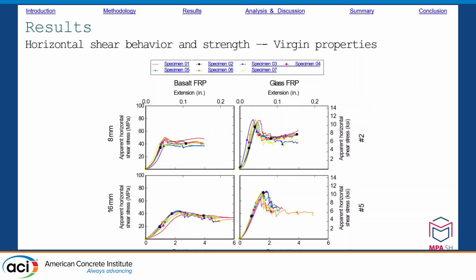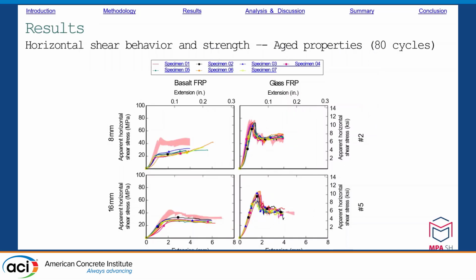The result graphs of the specimen tested for the apparent horizontal shear strength also show an increase until the maximum shear stress is reached. After that, the graph levels out and no further increase can be seen. The glass fiber rods achieve a significantly higher maximum value of shear stress compared to the basalt fiber rods. Compared to the bars with 80 freeze-thaw cycles, the maximum stress in the basalt bars is significantly lower. In the case of the glass fiber rods, this is only minimally lower. A clear drop cannot be seen.